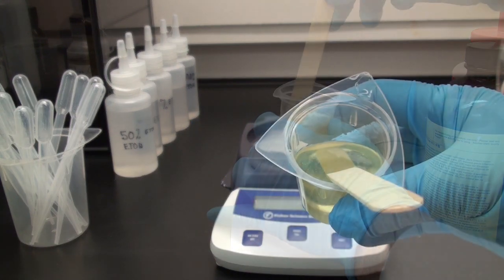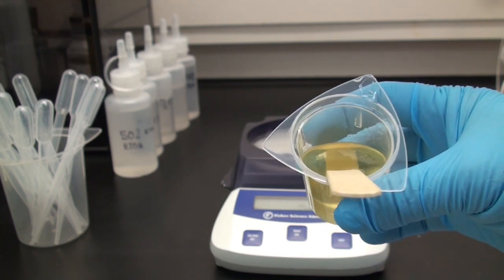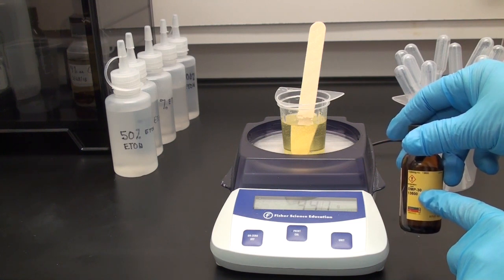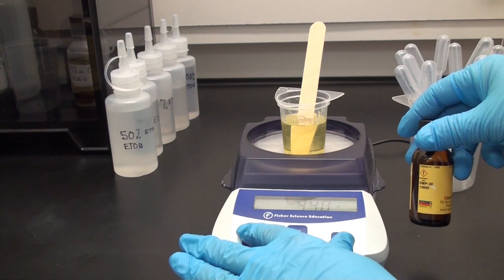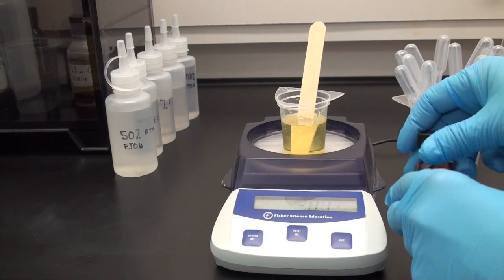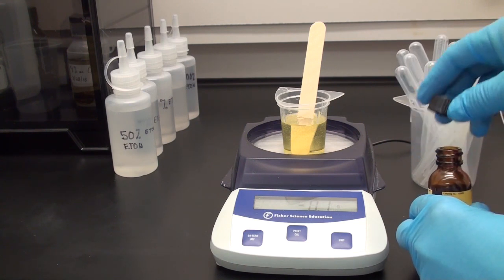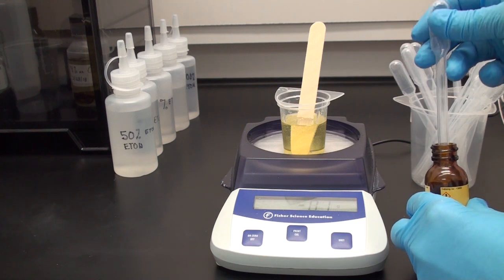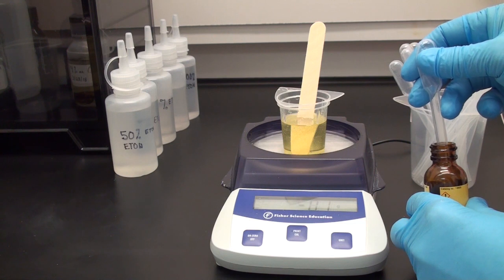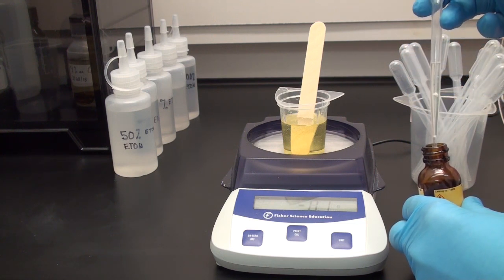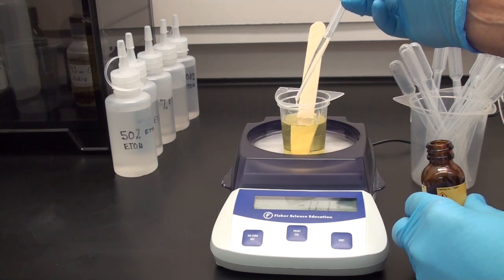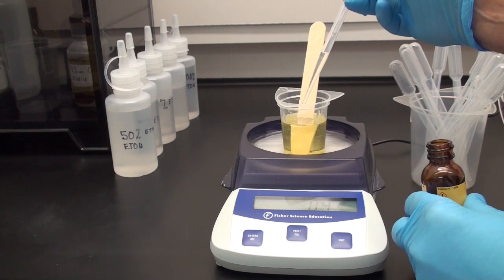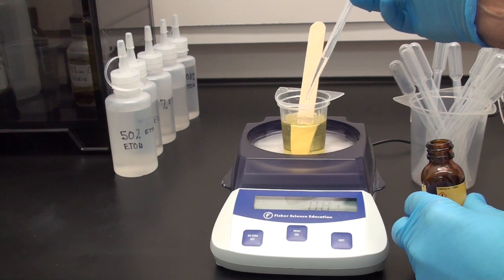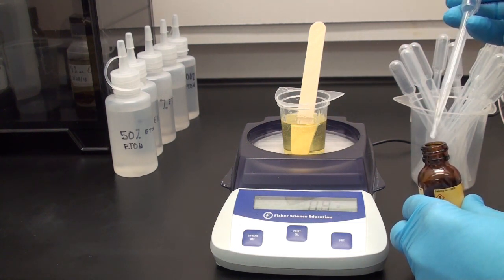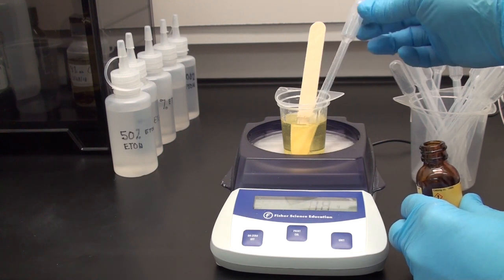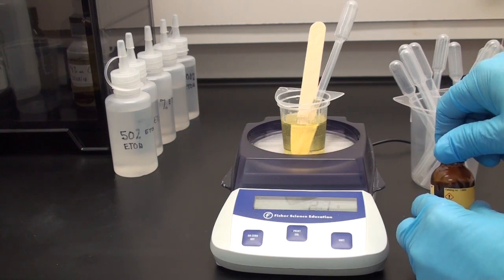Now, before I add the accelerator, I want to mix this up, and as I mix it up, I want to make sure I don't see any stir lines in there and get a good mix. I am using DMP30, and this is 2% or 2.5% of my total, so I made up 40 grams, and I'm going to put in about 0.8 to 0.9 grams of my DMP30. If you use BDMA or DMAE, they have different concentrations, so always read the instruction sheet that came with your individual resin. The final concentration of your accelerator is extremely important. If you put in too much, the block can be hard and also cause uneven polymerization. So I used about 0.8 mLs or 0.88 grams of this.